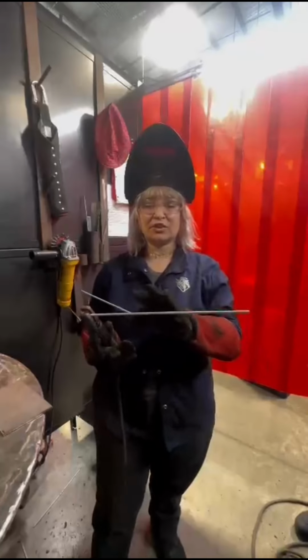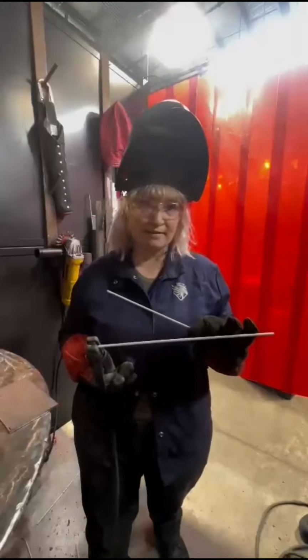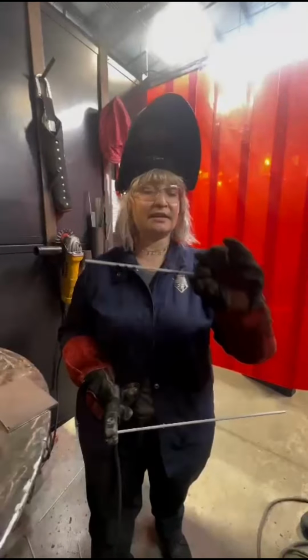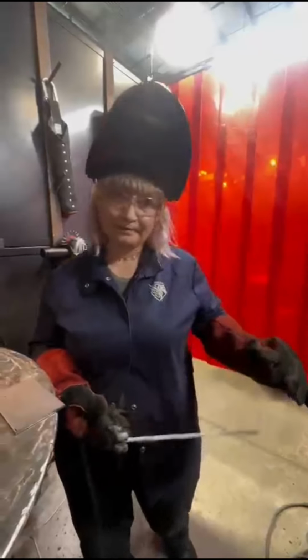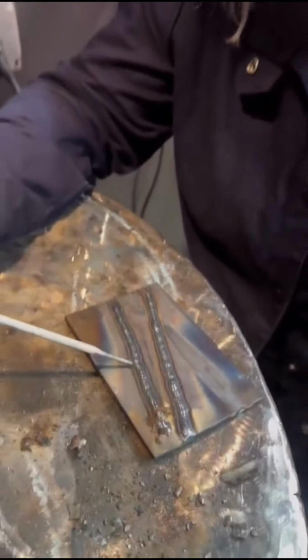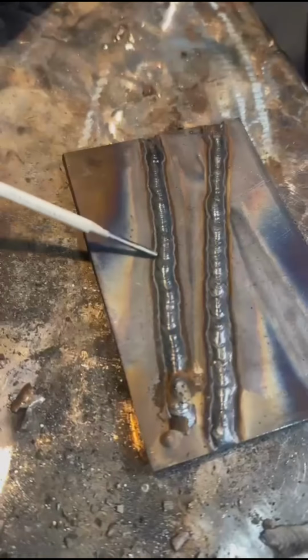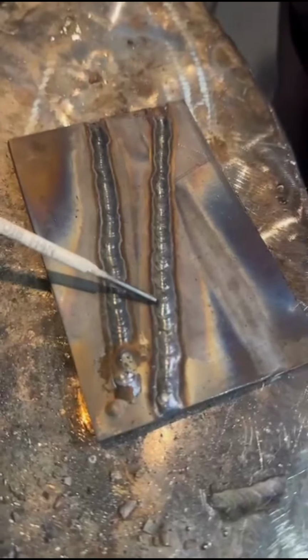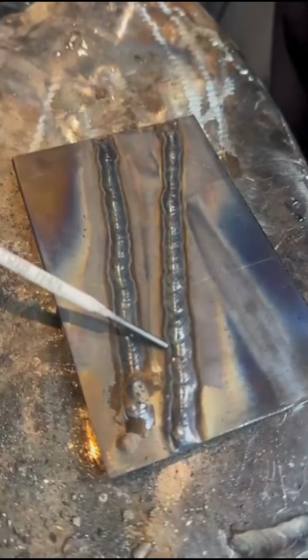Alright, so here we've got a 7018 electrode that's been in the oven, fresh out of the oven, how you're supposed to have them. And this one is fresh out of the dumpster. Who knows how long it's been in there, so it's definitely got moisture. We're going to show you the difference between the two. This is the electrode that we used that was from the oven. You can see that it's consistent and there's no porosity here. With this one, the electrode melted at different speeds, and there are points of porosity.